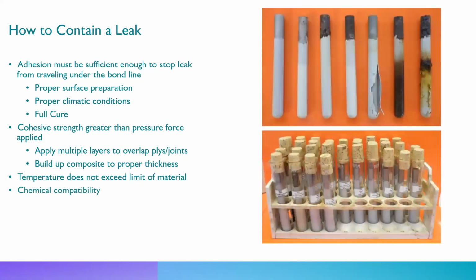And then finally, you're going to want to look at the chemical compatibility. If you have enough strength to hold in the leak, enough thickness to hold in the pressure, you can handle the temperature, you do everything right, but then you can't handle the chemical, it's not going to work long term. So we've got to make sure that whatever chemical is being exposed to the repair is not going to cause issues like you see here on the far right. This is one of the standard tests we use, ISO 2812-1. This is where we coat rods with our product and put them in test tubes with different chemicals and see how they react over a full year.